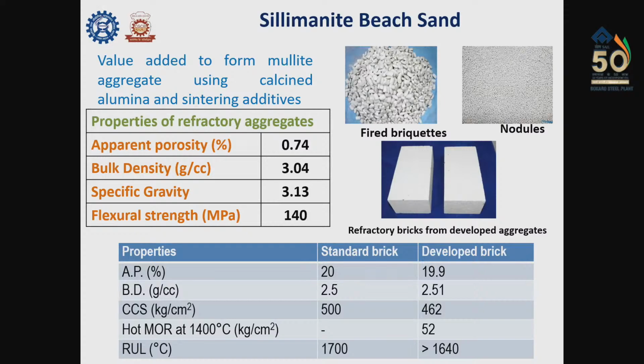With this aggregate, we prepared standard brick. We benchmarked this brick with the standard available commercial level bricks, and the results we have achieved are almost identical to the commercial brick. So sillimanite beach sand, which is a pure material, can be value added, because it cannot be used straight away as it is very fine. We got it in a very fine state. We need to convert it into aggregates, and we did it and achieved good results.